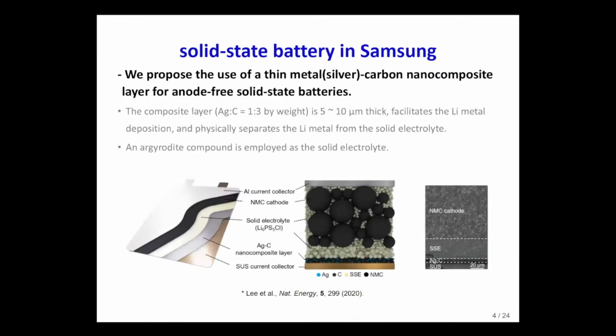Here's the design of our own solid-state battery. We employ a sulfide-based electrolyte, and the cathode is a composite, and the anode is a silver carbon nanocomposite. This silver carbon layer is 5 to 10 micrometer thick, and it facilitates the smooth lithium metal deposition.